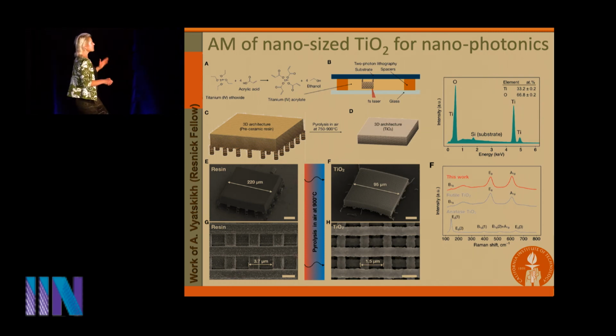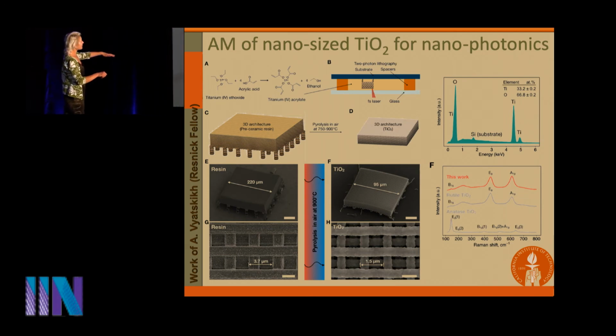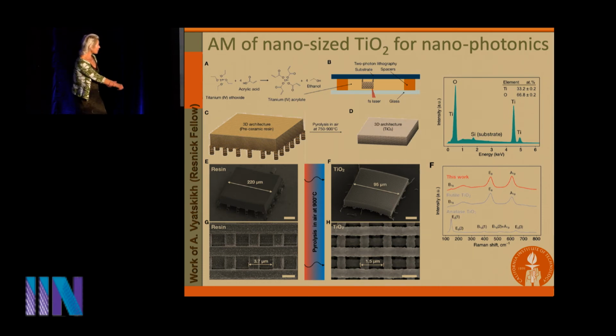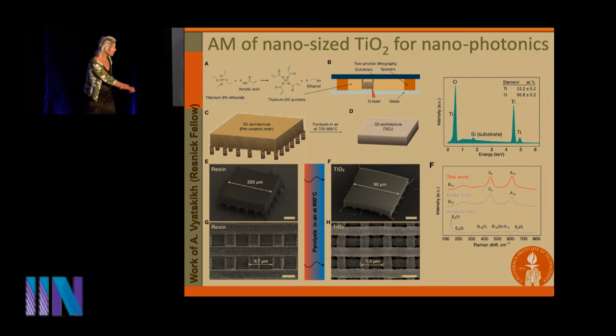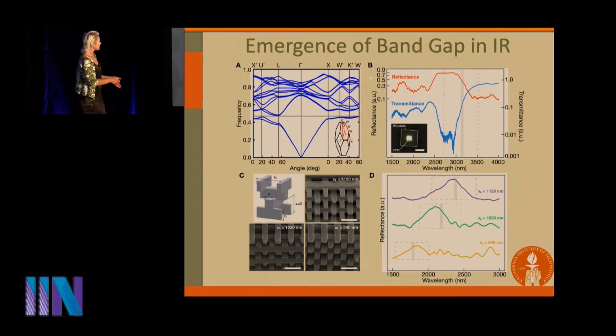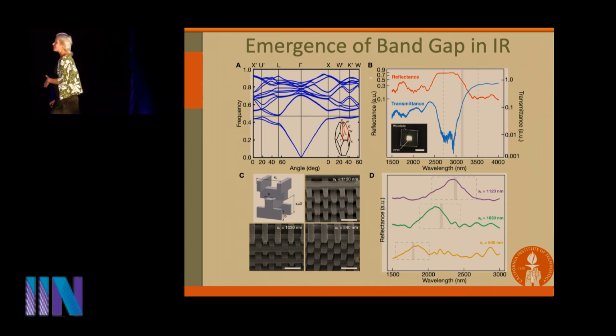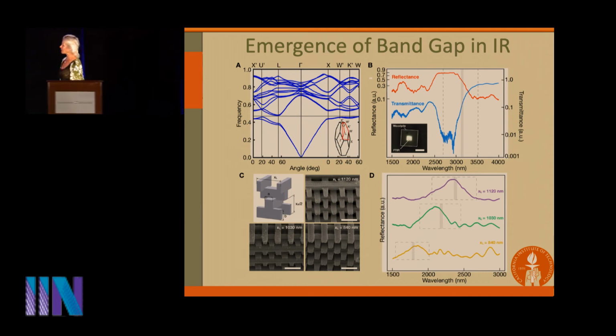So when you reduce the dimensions of these titania nanoarchitectures, again, here's the very bulky monomer that ends up here. And then once you use 2-photon lithography to create these at the smaller scale, you can see now the resolution here is only 1.5 microns. So we're reducing it back down to the nanoscale. You can see the emergence of a photonic band gap in the IR, and you can see that this band gap is shifting as a function of the periodicity of these structures. So titania, of course, is a high index material, so you can do quite a bit in the realm of nanophotonics using these additively manufactured materials.